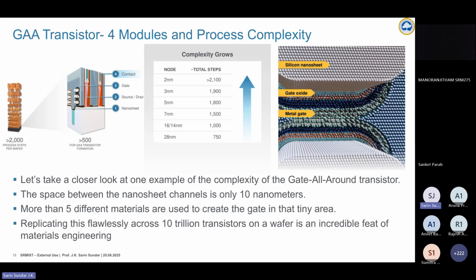Also, if you look between the 2 nanosheets on a typical gate-all-around transistor, between here and here on this picture on the right, the typical thickness is only about 10 nanometers. And in this 10 nanometers, there are 5 different materials. These need to be deposited and removed in a very precise fashion, and also inspected for defects. And this is already going, and it has to be done repeatedly across 10 trillion transistors on a single wafer. That's a huge amount of inspection requirement.